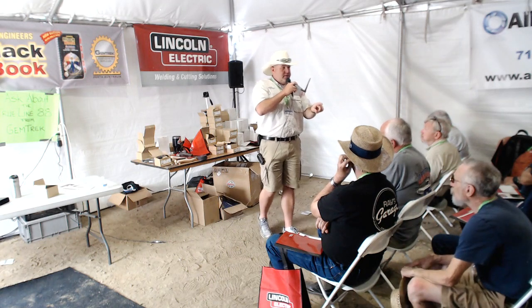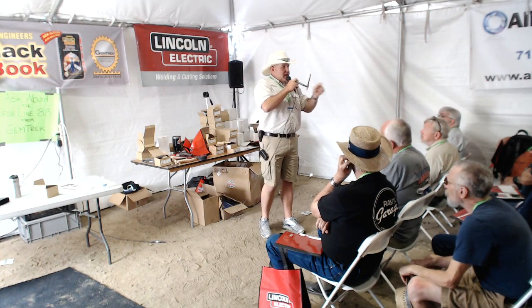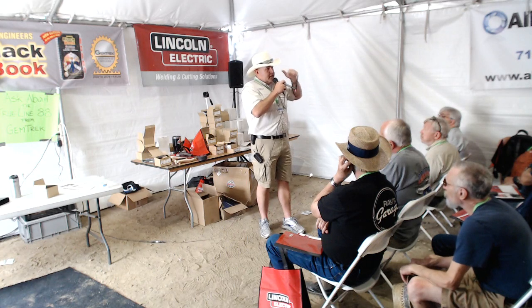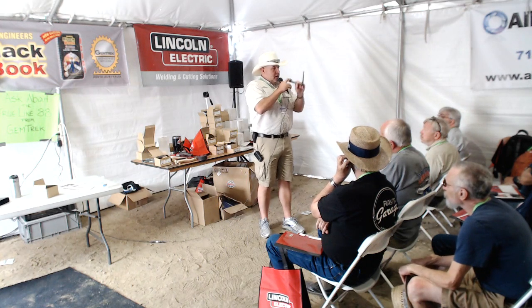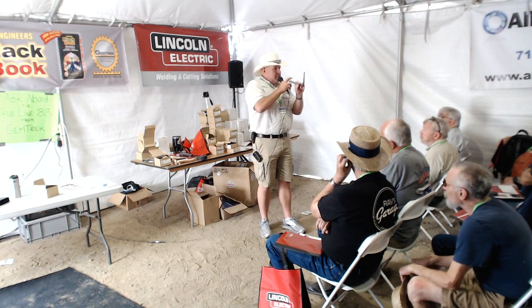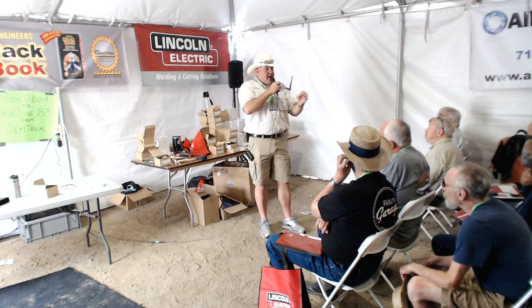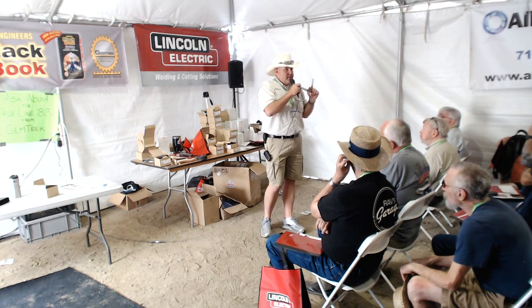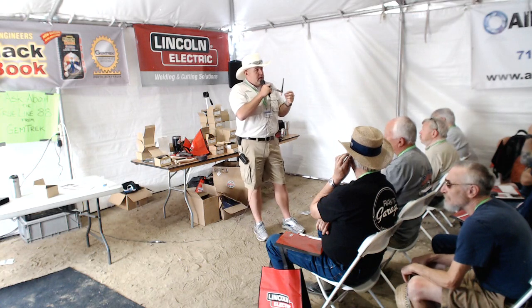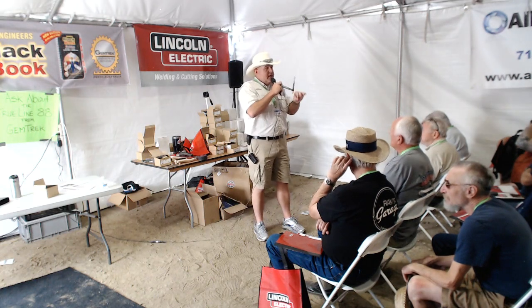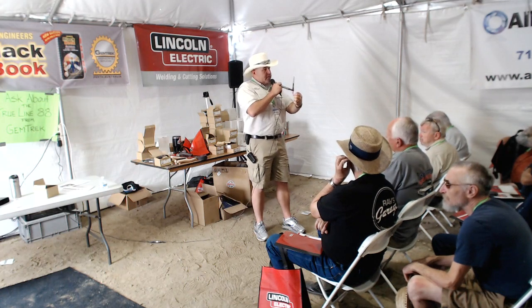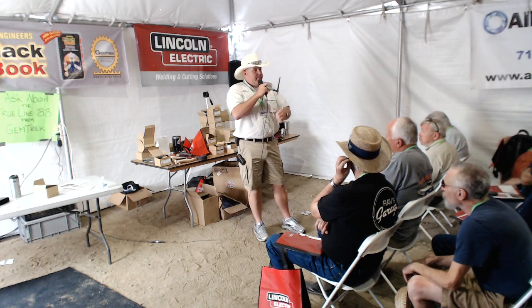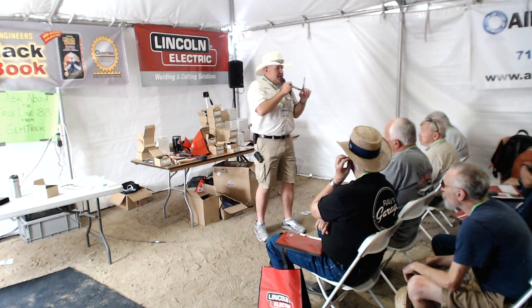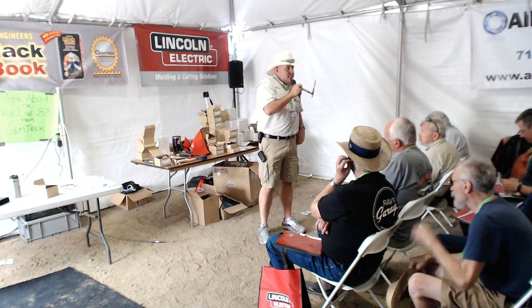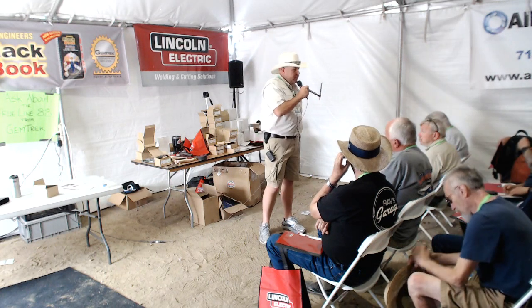Well, sort of, yes. Filler rod. As we pull the filler rod out of the puddle, it's molten on the end of the rod. So that little bit of back angle puts a little bit of argon out and gives that a second to freeze so that it doesn't pick up contamination from the atmosphere. And ideally, you should be keeping that filler rod right in that plume the whole time. Not everybody does it as a beginner, and I get that. This isn't an advanced class. This is a beginner class.